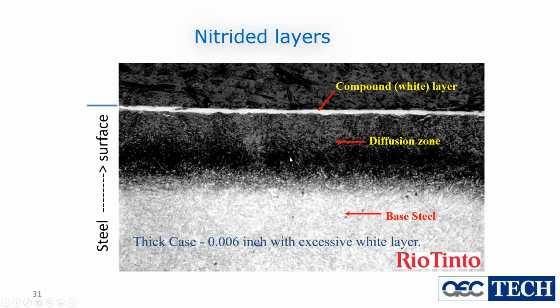If you have a very thin transition zone, it means that your nitride layer is not being bonded well with the base metal. You're going to have cracks between them after a couple of thermal shocks, heating and cooling. The best practice is to have a very thin white layer and a thick enough diffusion layer, because if the diffusion layer is too thick, I'll show you what happens. You may end up having cracks all over, and if these cracks get bigger than a critical size, they can grow into the base metal and fail the whole thing. So the good case thickness is about 6 thou.